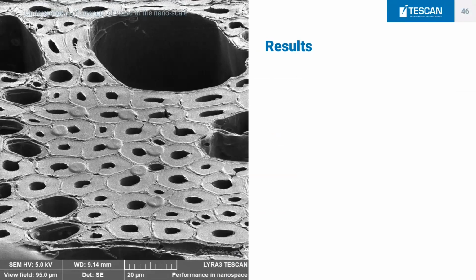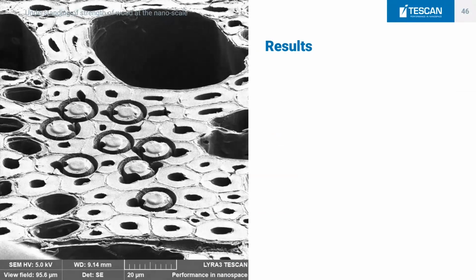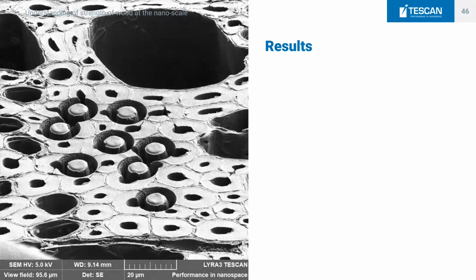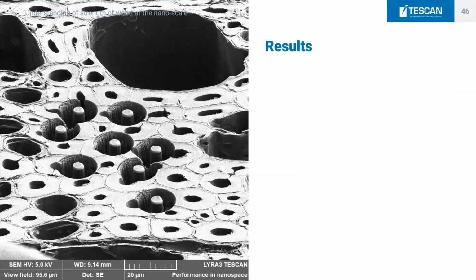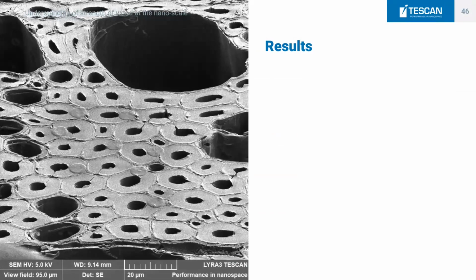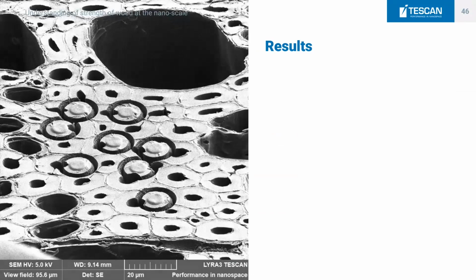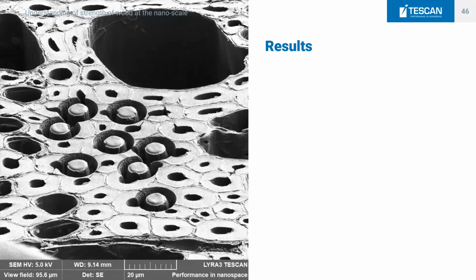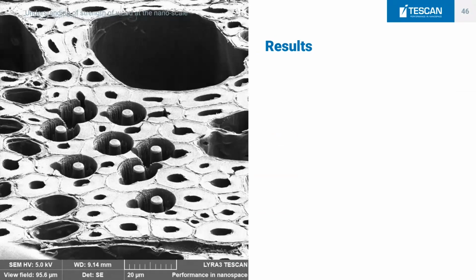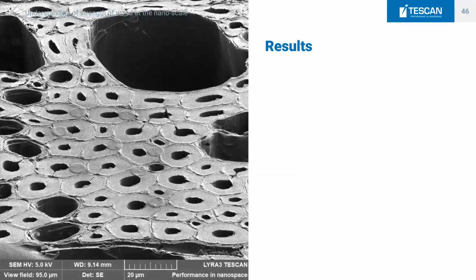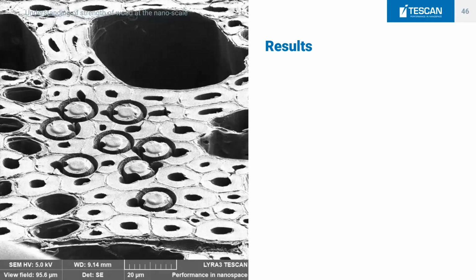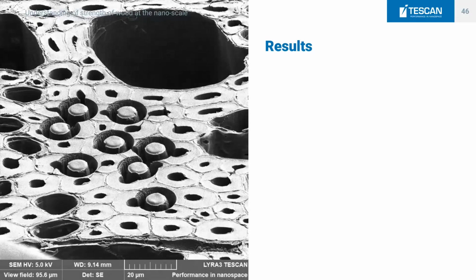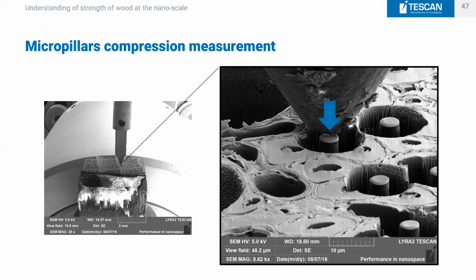So what you could use a FIB-SEM for is that you could create micropillars like this. You could focus on a specific area of interest and create small pillars, which you could test afterwards inside of the system like this. So we use the focused ion beam to create the smallest compression specimens, which were, I believe, around 10 micrometers wide.